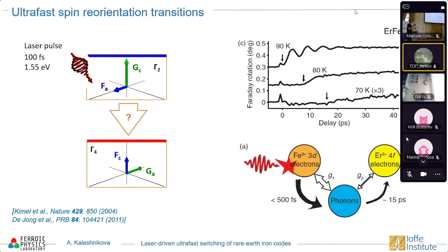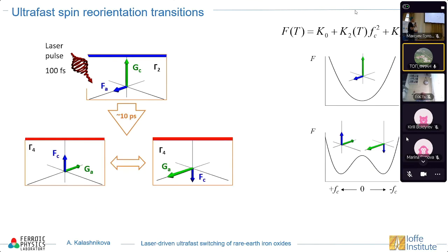So is it good or bad? Actually, we can try to use it. In principle, laser-induced spin reorientation transition seems to be a nice way to really switch magnetization. So we start from the low temperature phase, we excite the material, and we switch it to another phase. But the problem is that if we don't have an external magnetic field, and typically we don't want to have an external magnetic field, then in principle switching will happen from this minimum to either this or this minimum of our potential energy.